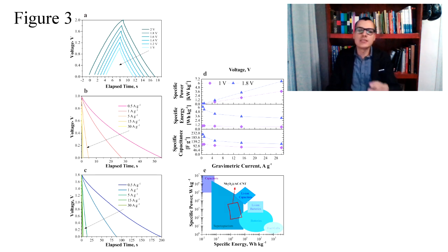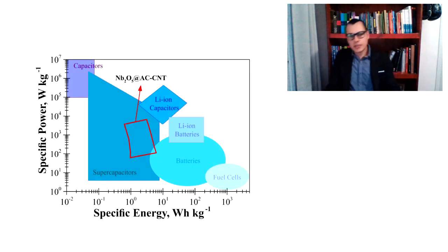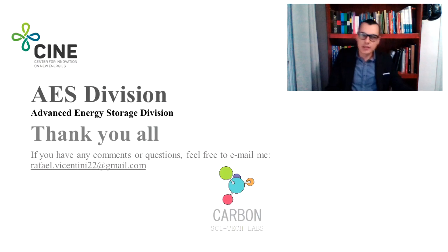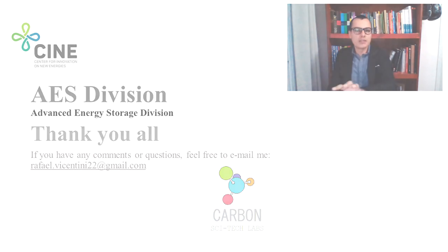It's worth mentioning that the literature usually reports niobium-based electrodes for supercapacitors up to 10,000 cycles, so this is a much higher cyclability. Besides high stability and cyclability, this device has high specific capacitance and high energy and power densities. And that's why we use these carbon-based materials decorated with niobium in operando studies.